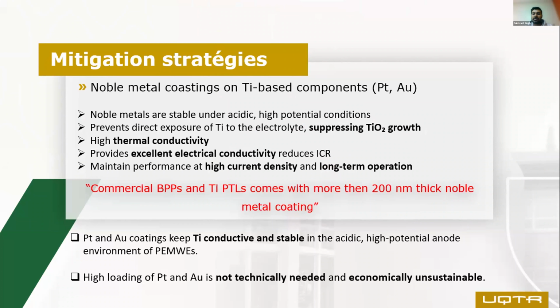Because noble metals are highly stable under acidic and high potential conditions, this prevents direct exposure of titanium to the electrolyte, suppressing titanium oxide growth. These metals have high thermal conductivity and provide excellent electrical conductivity. Finally, this results in a reduced ICR, which is interfacial contact resistance, and also maintains better performance at high current densities during long-term operations. And these coatings make these components economically unsustainable, highly costly.